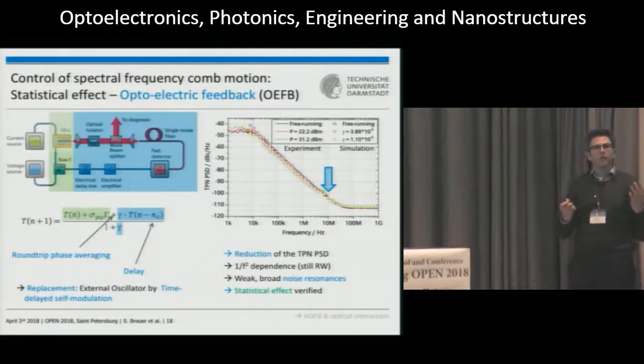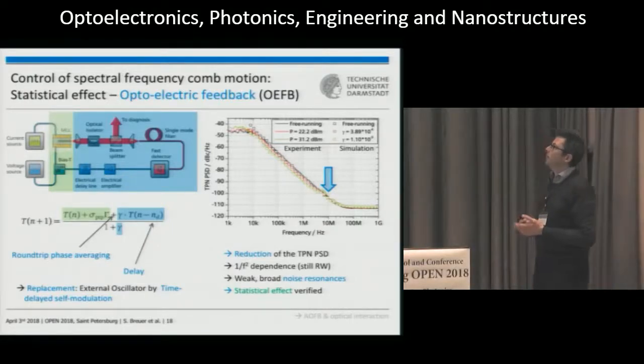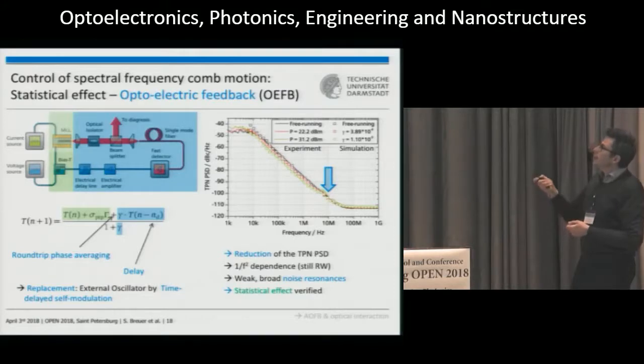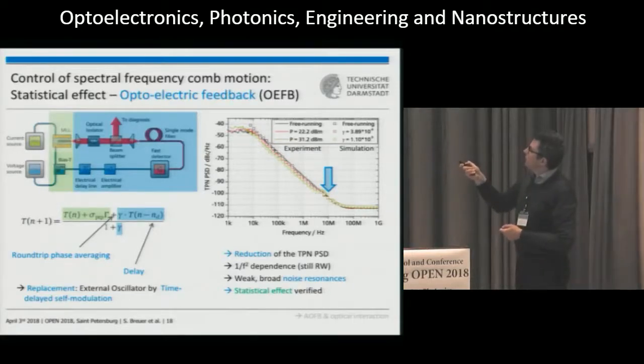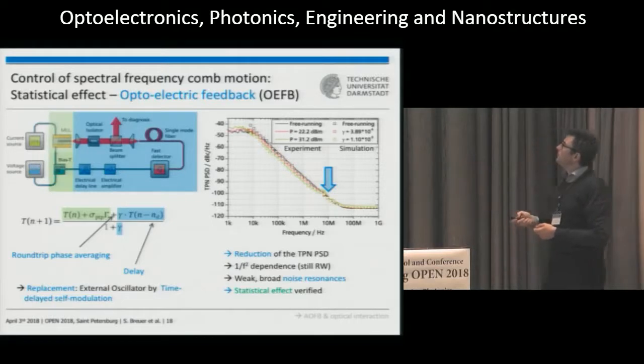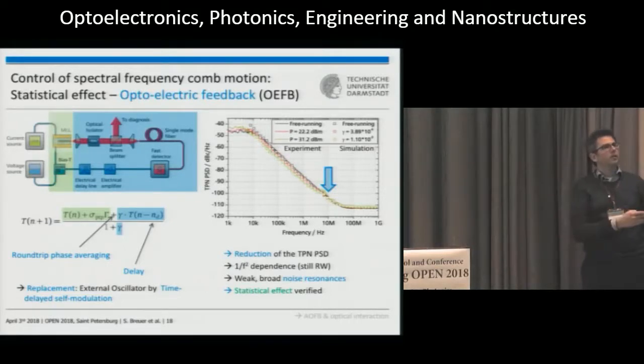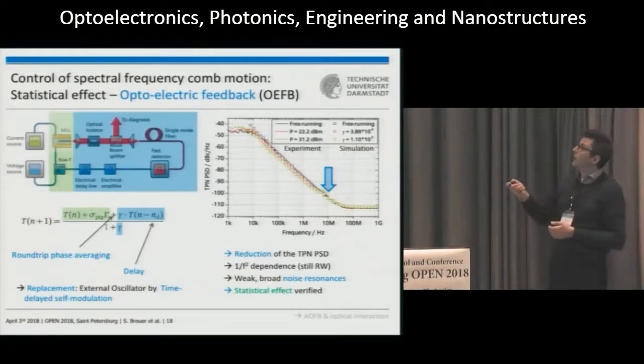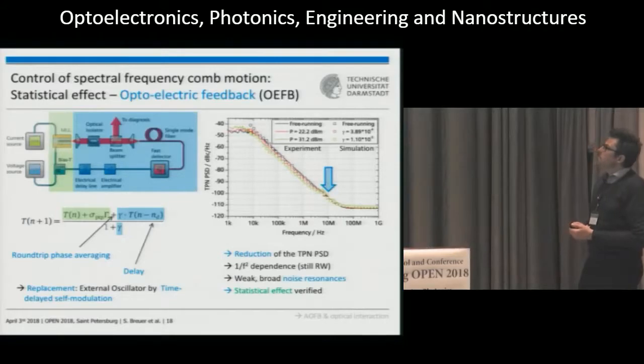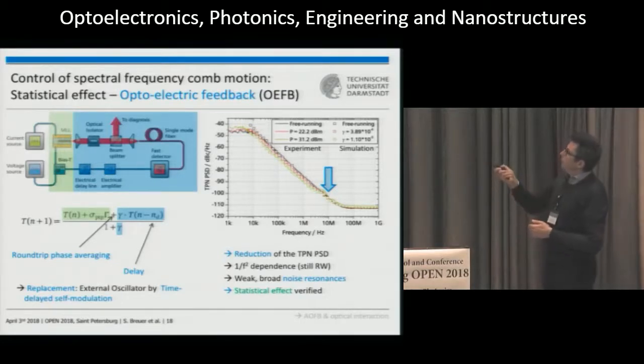So it's some kind of self-delayed or delayed self-modulation. Again, in the timing phase noise power spectral density, we find quite good agreement. If you look closely around 10 megahertz, you see a small deviation. This small deviation is the sideband noise resonances induced by this external cavity, which is quite nice because it also confirms the statistical effect that we assume. We have the 1 over f squared dependence, so that is still quite nice.